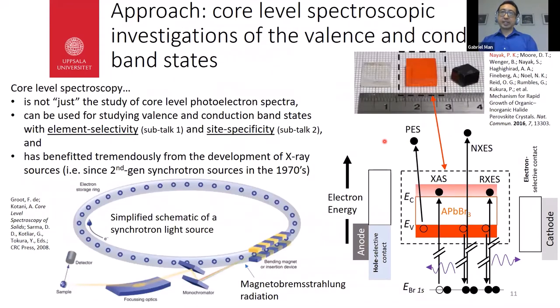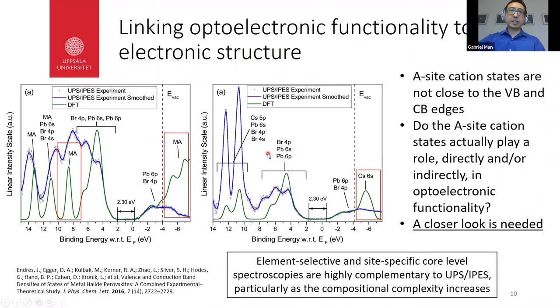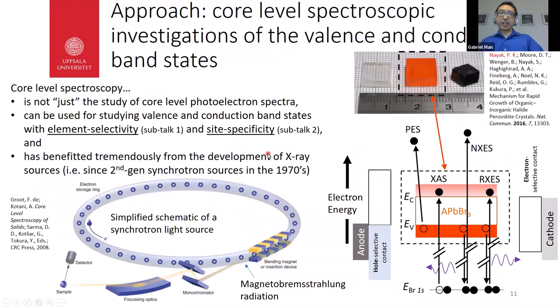So the approach I've taken is to apply an array of core level spectroscopies. Core level spectroscopy is not just the study of core level photoelectron spectra. It can be used for studying valence and conduction band states with element selectivity, which I've exploited in subtalk one, and site specificity, which I've exploited in subtalk two.